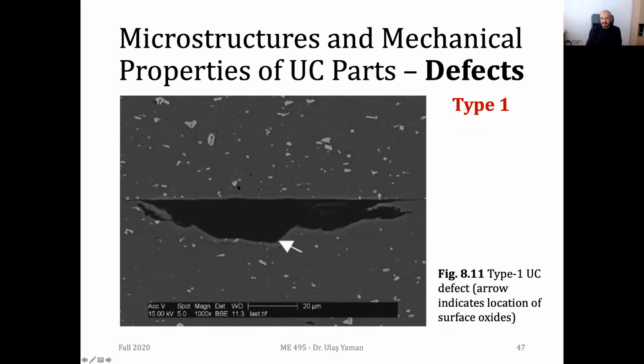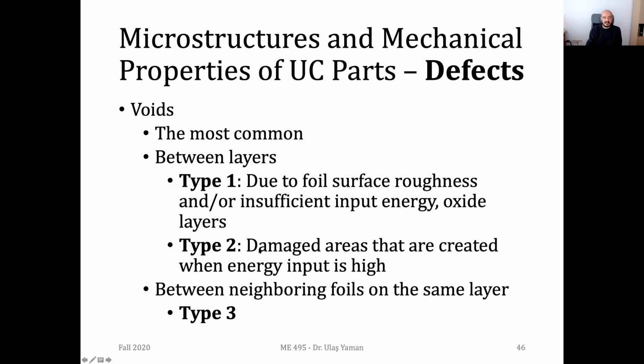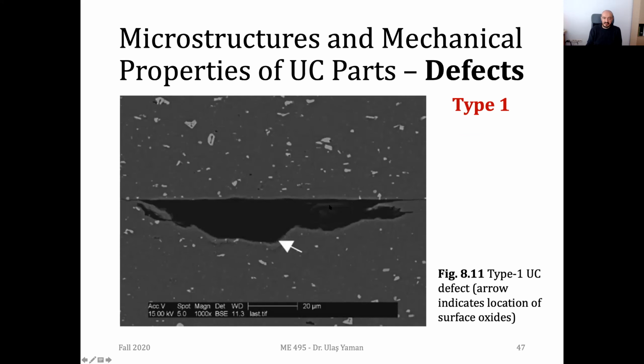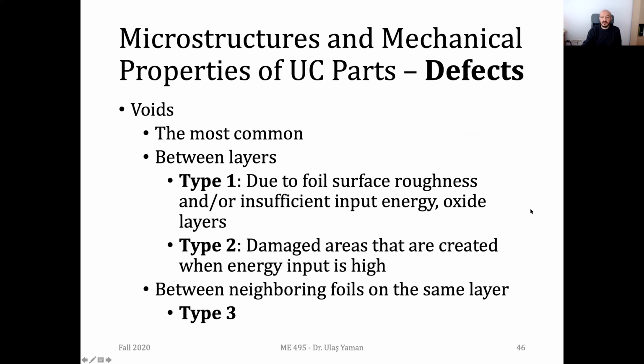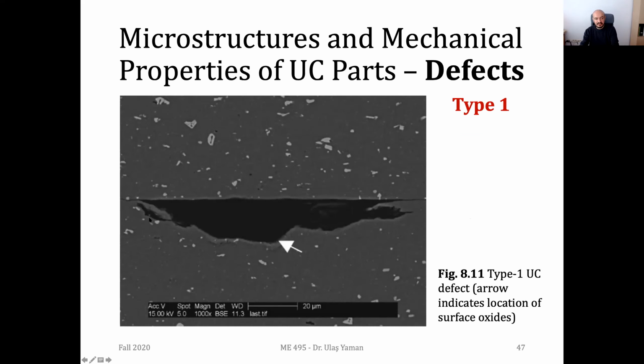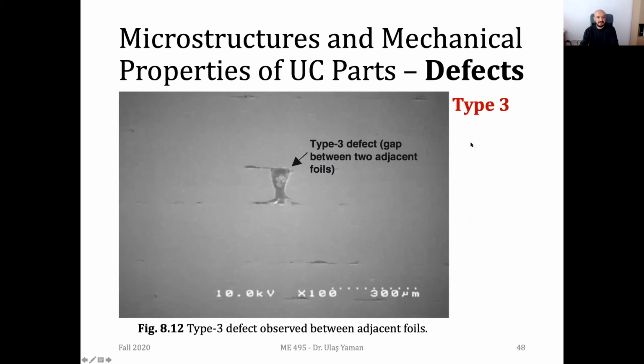Now let's have a look at these. This is the first type of defect, and you can see some surface oxides here, and these are actually resulting in such irregular shapes between the layers, and this part will not be able to join to the previous layer. And if you look at our type 1 definition, it's due to the foil surface roughness, insufficient energy, or oxide layer. So we have oxidation here, and that's why it's called a type 1 defect.